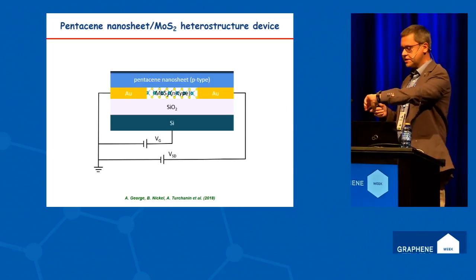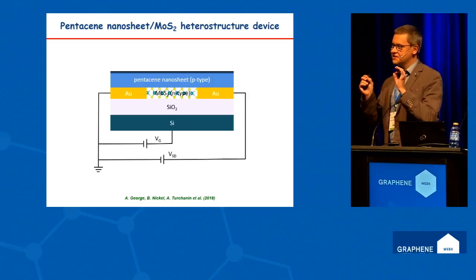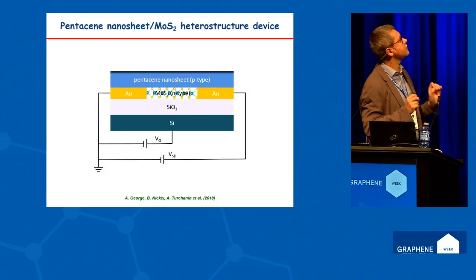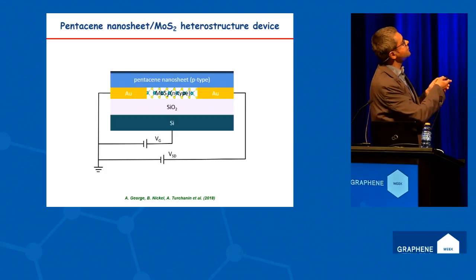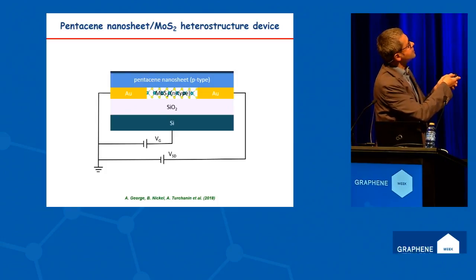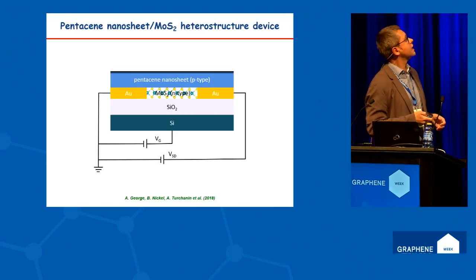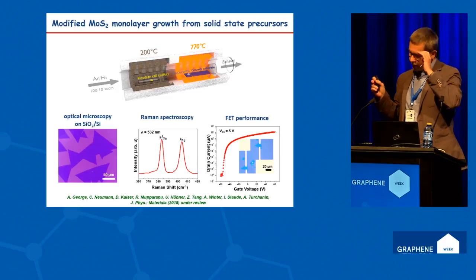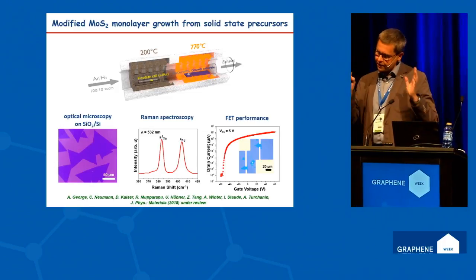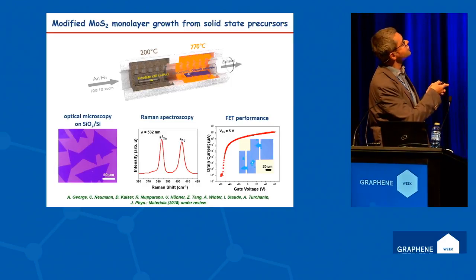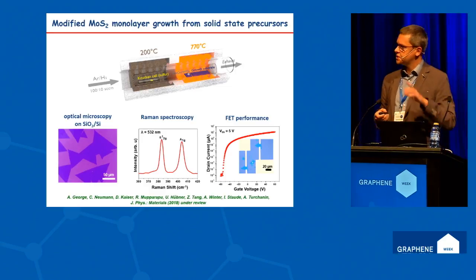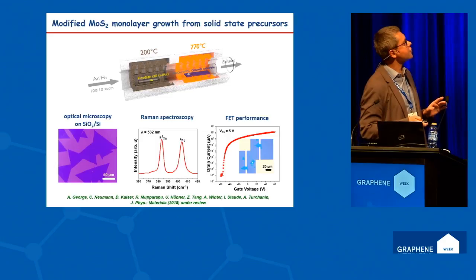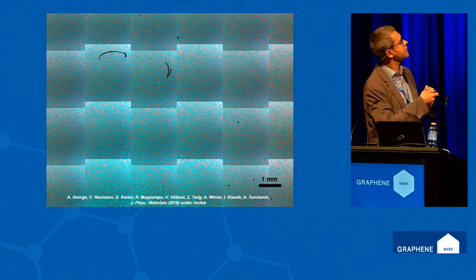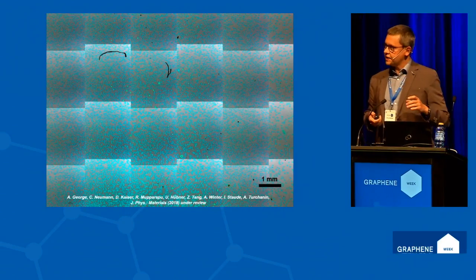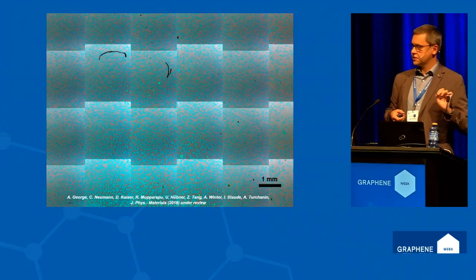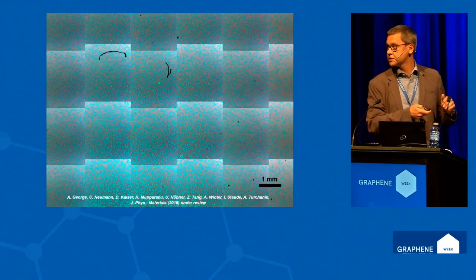Well, now in the last 4 minutes, I come to the description of a very simple device which we realized to study. We combined in such a field effect device pentacene and molybdenum disulfide as channel, these 2 materials. Very briefly, in this project we also developed the growth of molybdenum disulfide, introducing in the CVD reactor a so-called Knudsen cell for the precursors, which results in much higher reproducibility of the growth of TMDs. This is, for example, about a 10 by 10 millimeter layer of silicon oxide, where nearly monolayer crystals of molybdenum disulfide were grown with very little inclusions of multilayers.